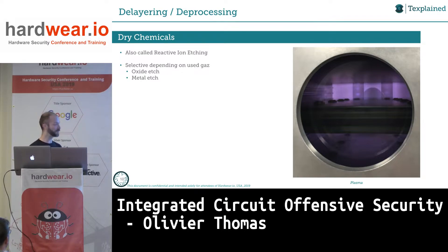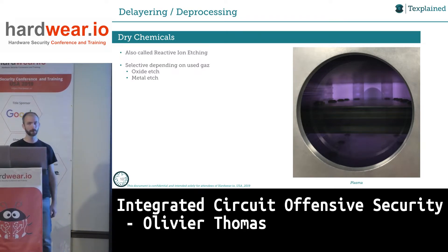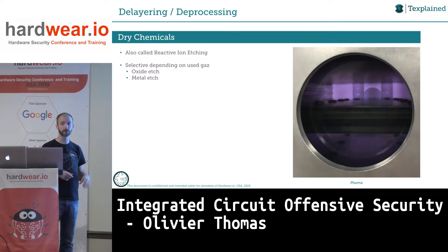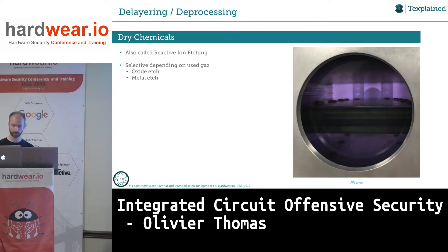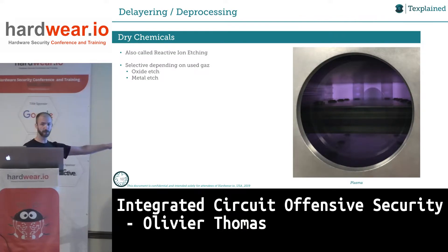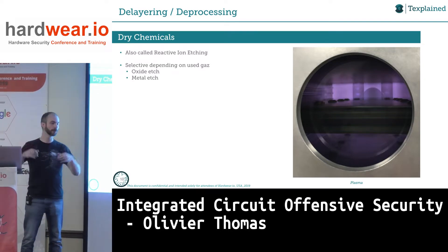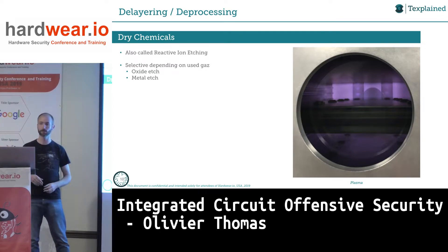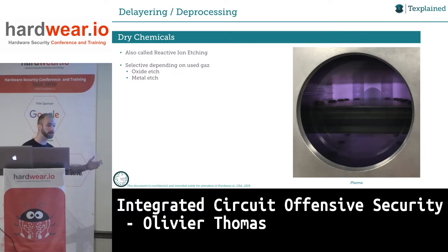Plasma etching is something quite nice. You create a plasma by exciting a gas to separate electrons from the other parts of the atoms. Depending on the gas, you can remove oxide or metal, which gives you a lot of precision. It's slow enough that you can control and check your results. But if you do only plasma etching it won't work either, because it will nicely remove oxide layers but as you continue the line profiles get very messy and you end up exposing several layers.